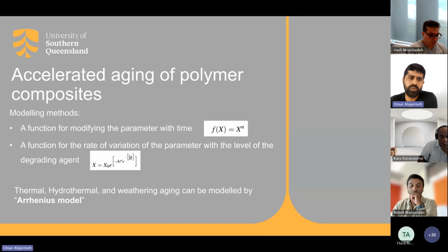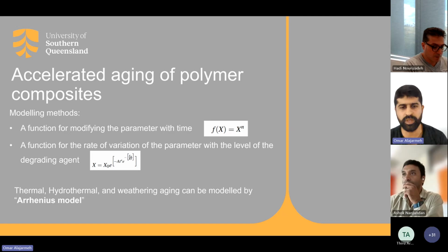type of aging. However, if you are looking for a function for the rate of variation of the parameter with a level of degrading agent, this is when we are looking at physical and chemical aging. So we need temperature, and we need time with the temperature, and we need something called activation energy, which will come after this slide. Apart from that, we are focusing more on the Arrhenius model as a model that can describe some of the thermal, hygrothermal, and weathering aging of the composite material.